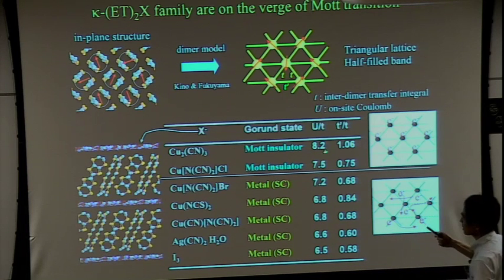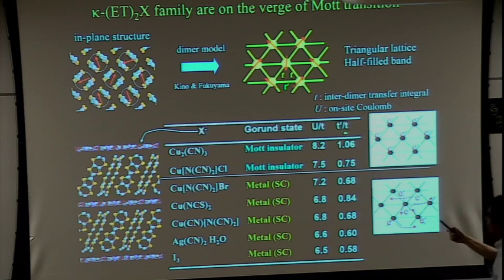By changing the anion species, U over T also changes—highly correlated in some cases, and correlation is very small in others. T prime over T, the degree of fluctuation, is also largely varied depending on the molecular species in the anion layers. These materials form a nearly triangular lattice.